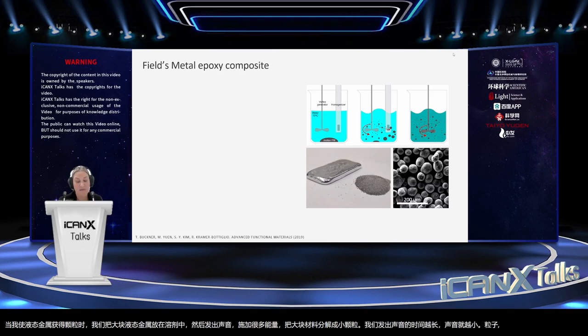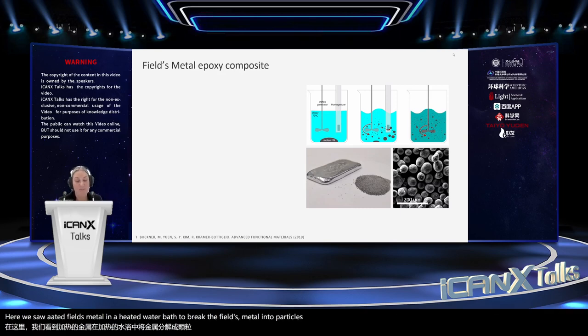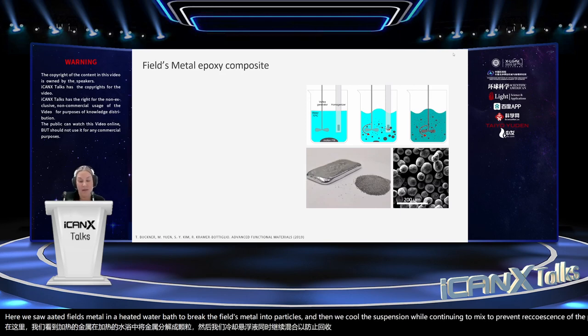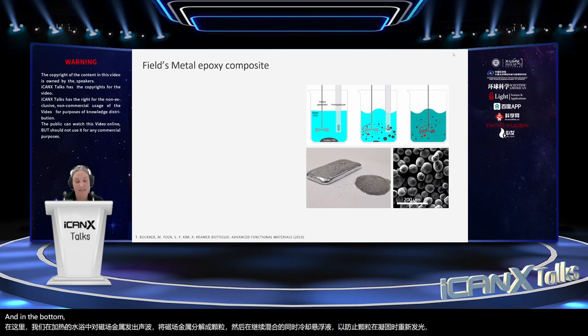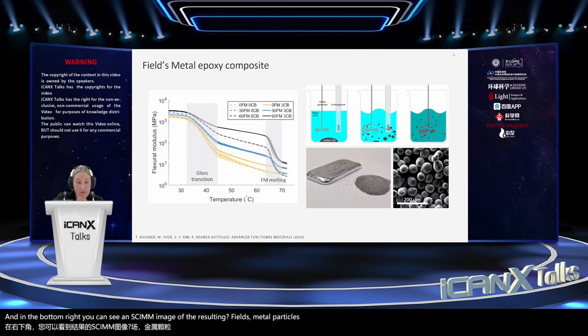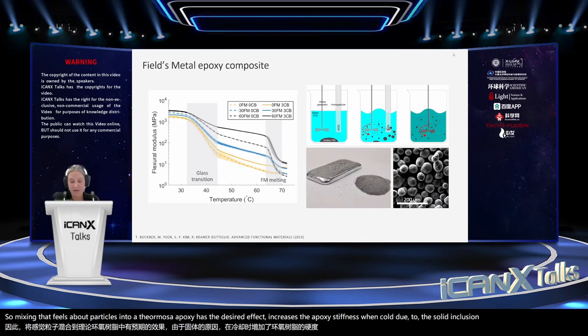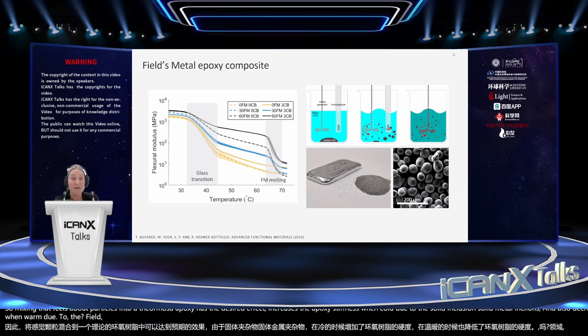Here, we sonicated Fields metal in a heated water bath to break the Fields metal into particles, and then we cooled the suspension while continuing to mix to prevent recoalescence of the particles while solidifying. And in the bottom right, you can see an SEM image of the resulting Fields metal particles. So mixing the Fields metal particles into a thermoset epoxy has the desired effect. It increases the epoxy stiffness when cold due to the solid metal inclusions, and also decreases the epoxy stiffness when warm due to the Fields metal particles melting at 62 degrees Celsius and becoming liquid inclusions.